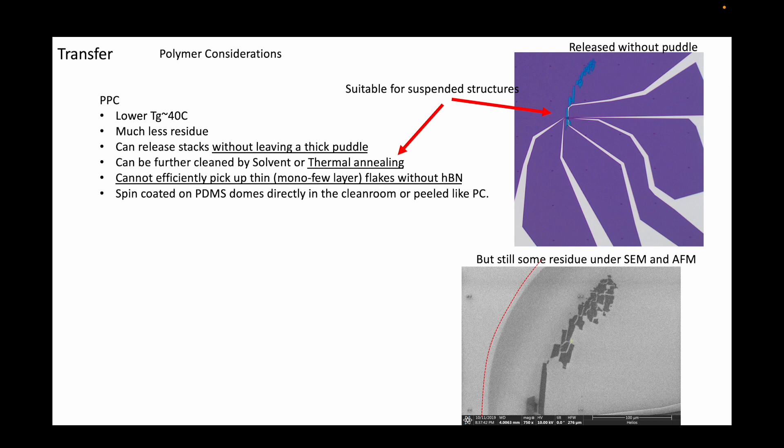The disadvantage of using PPC is that it is not as sticky as PC and therefore cannot pick up monolayers. And even if you tried, it would cause too much stress to the 2D flakes due to the large thermal expansion coefficient.